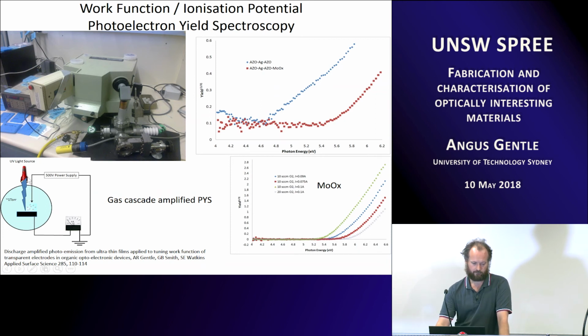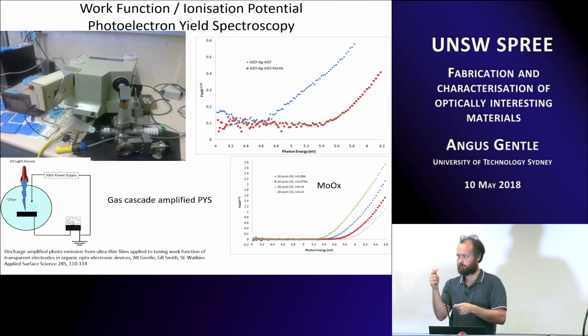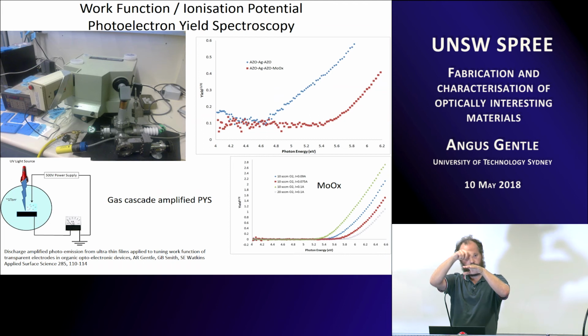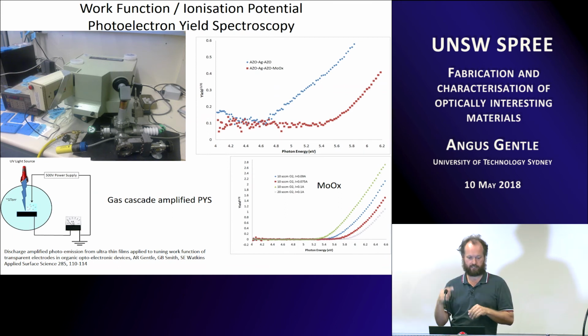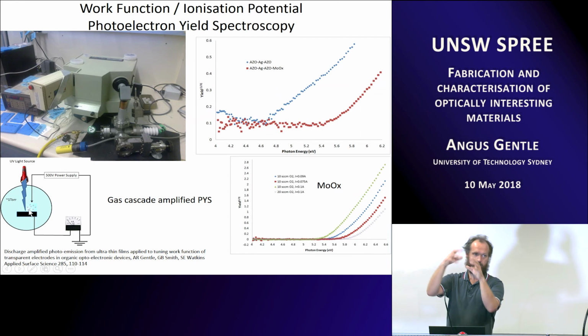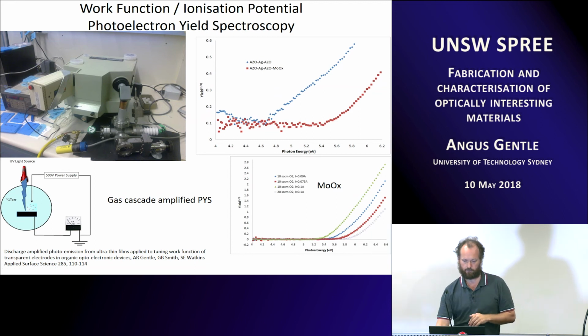Basically, you've got a UV light source that comes in, a vacuum chamber, which is at a not particularly good vacuum. So it's basically a roughing pump with a little needle valve here that's set open. Measuring the pressure. This is all set up really small because it was designed for doing our single slides, little 1-inch square slides. You've got a 500 volt probe above the stage, and then the stage is earthed through an electrometer, so it's a picoammeter to measure how much current is going through, and it's gas cascade amplified, so basically works the same as your ESEM detector in your electron microscopes. So you end up getting an electron comes out, ionizes the gas, and then it continues to cascade, so you can measure a current that comes through.